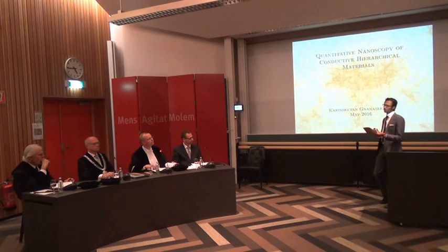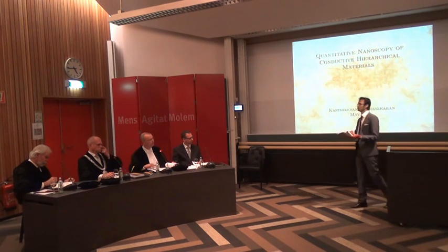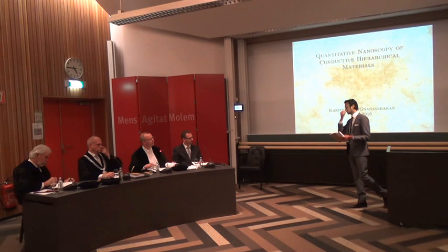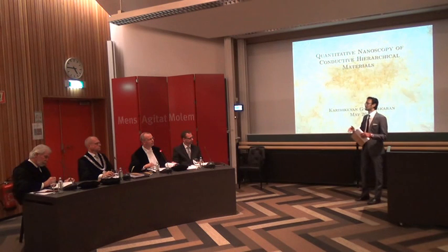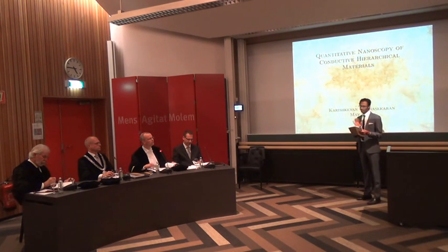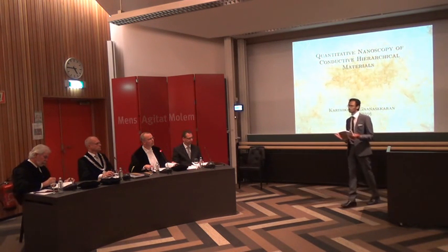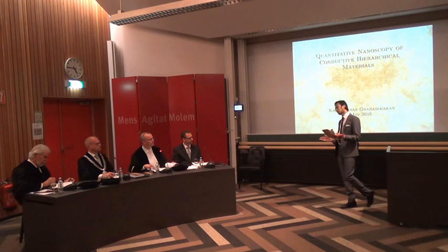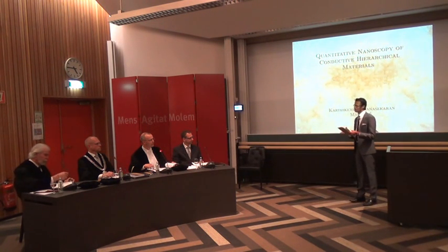So that model may give a different answer when you are checking with the 100 nanometer thick section, because at high angles it won't get scattered to high angles. In the 100 nanometer thick section, the scattering will be less at high angles. So I believe the model also plays an important role. So depending on the section thickness, we have to change the model also. That could be another explanation, another reason for this shift.